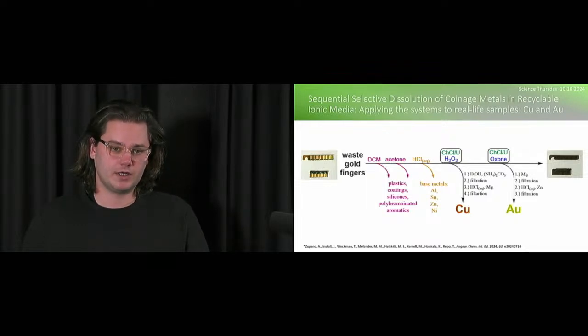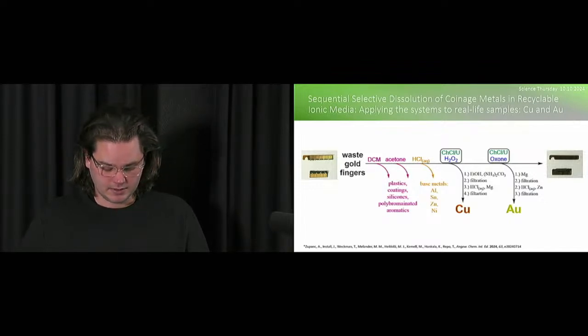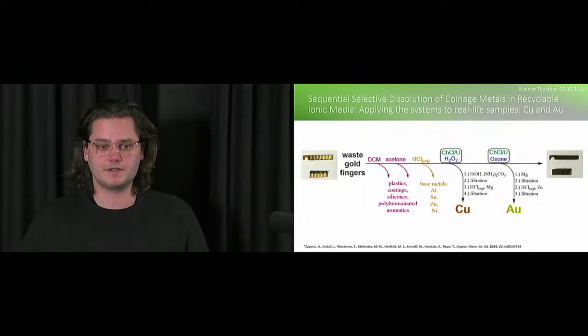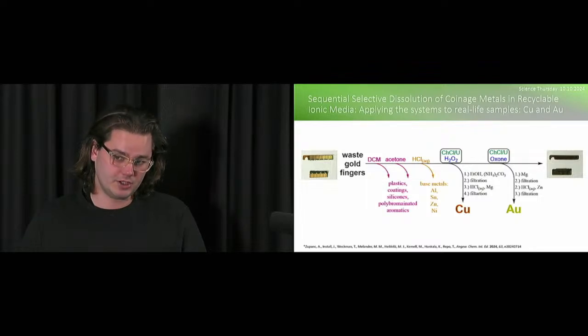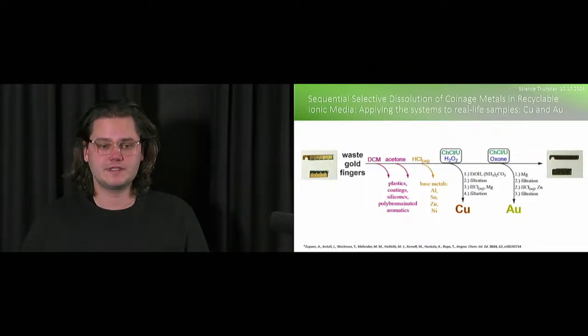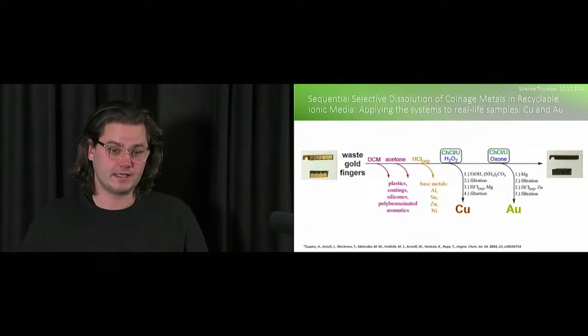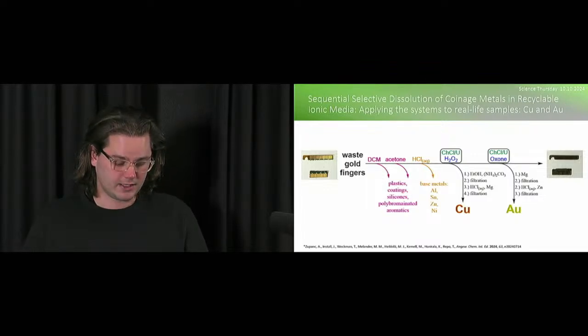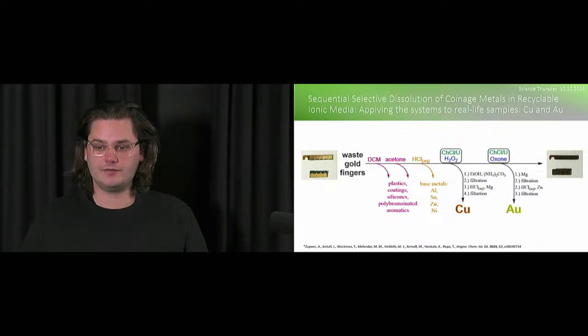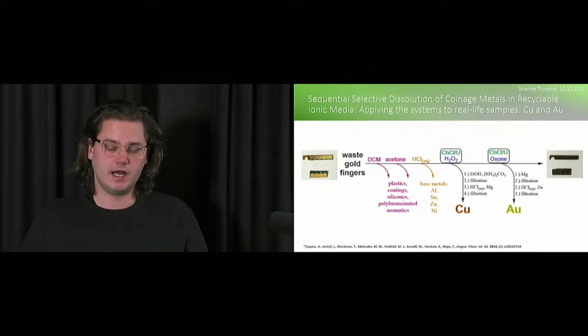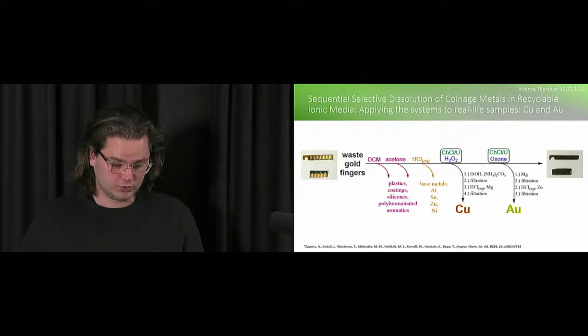So first we used some organic solvents just to get rid of the plastic coatings and silicones and polybrominated fire retardants, and then we used aqueous HCl to dissolve base metals like aluminum, tin, zinc and nickel. Of course, then we could apply our choline chloride urea system that selectively dissolves copper, and we dissolved copper and closed the recycling loop, as I showed you in the previous slide, to get back elemental copper. After that, because there was no silver in our samples, we could directly apply this system to dissolve gold in this choline chloride urea oxone system as I showed you before, and by closing the recycling loop we got out the elemental gold.